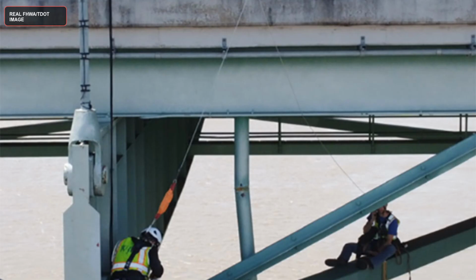The practical problem is timing. Fatigue cracks usually begin far smaller than an unaided visual inspection can resolve, and they can start on an inside surface or beneath a coating. That is why bridge and aircraft rules specify access, method, probability of detection, and crack growth data. Visual inspection may be followed by magnetic particle, dye penetrant, ultrasonic, or eddy current methods, chosen for the material and geometry. An inspection interval is not just a calendar habit. It is a calculated opportunity to find a crack before its remaining ligament loses the required capability.